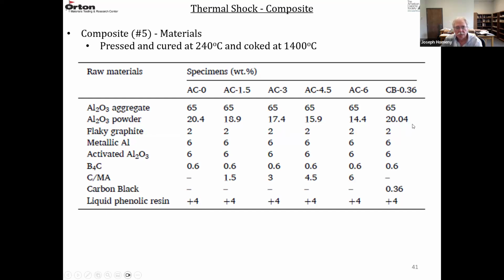And this last one had 0.36%. This is nano carbon black. And it actually has the same carbon content as AC 4.5. So if you take about 8% of this 4.5, you're going to end up with 0.36. So they put this one in just to look at the difference between a nano carbon black and a nano graphene that's in these aggregates of basically spinel. So AC 4.5 and CB 036 have the same carbon content.